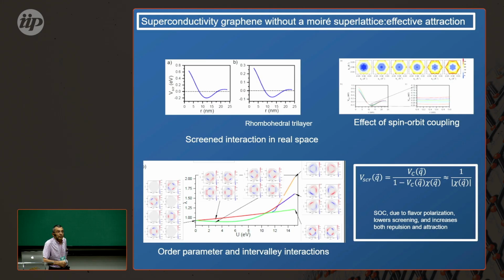If you add spin orbit coupling, you kill one of the half of the bands. The screening becomes lower, the interactions become more repulsive, but you increase both the repulsive and attractive parts, and that's why you get an increase in superconductivity, because superconductivity only cares about the attractive parts. It doesn't matter that the peak at Q equals 0 is stronger.